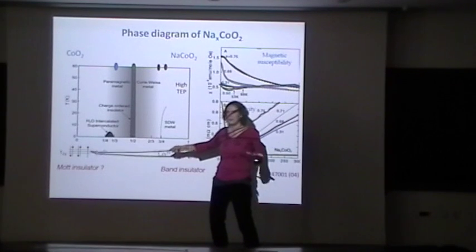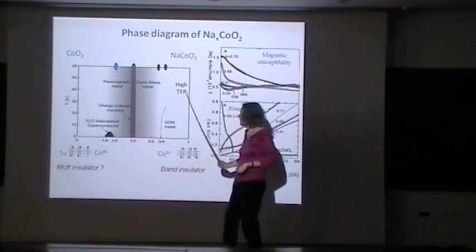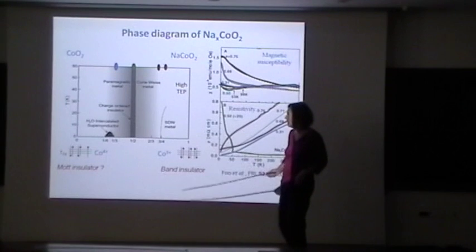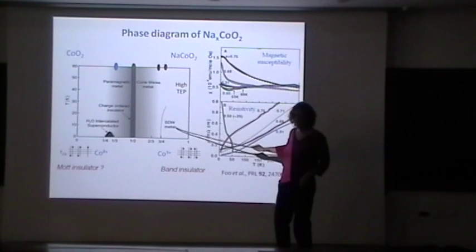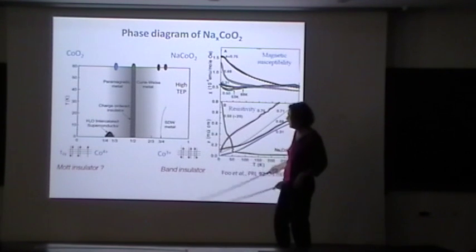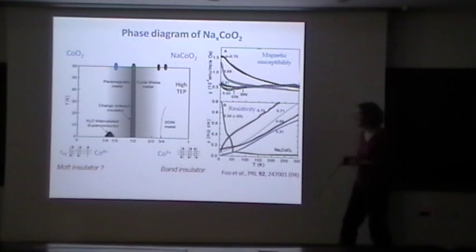should have strongly decreased because you're quite far from this Mott insulator, that you seem to have this sign of magnetic correlation. And it's also there that you find some spin density wave ground states that are telling you that you've got some magnetism in this phase.